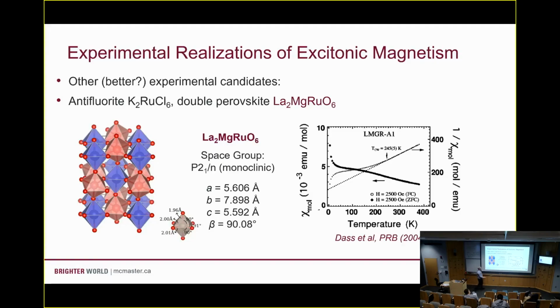And more importantly for us, the susceptibility that's been reported for this compound has identified it as having a non-magnetic singlet ground state. Okay, so it has weak Van Vleck-looking magnetism that's a little bit masked by impurity effects. So again, because of the possibility of swapping some of these magnesium and ruthenium ions here, you do end up with some non-magnetic or magnetic impurities. Typically, it's around the 2 or 3% level. Okay, so there are some free spins here, but most of the spins we think are non-magnetic.